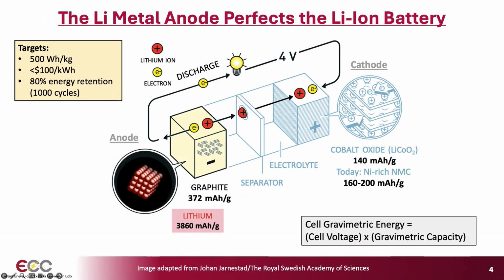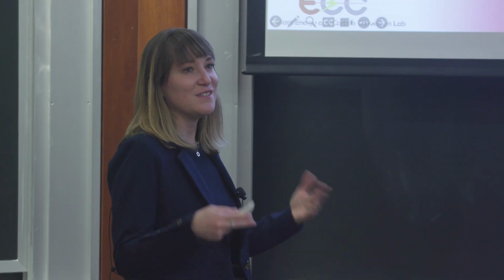However, it has always been and still remains the so-called holy grail in the field to be able to move from graphite anodes to lithium metal. And this is for a simple reason. Lithium metal is the densest way to store lithium charge, and you see that reflected in the gravimetric capacity. It's 10 times higher than that of graphite. Meanwhile, its redox potential is effectively the same as that of graphite, so we can retain high cell voltages.